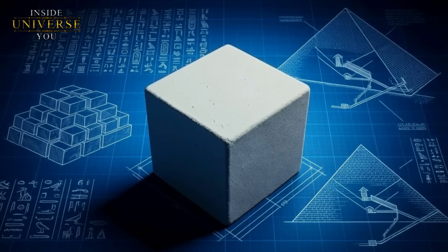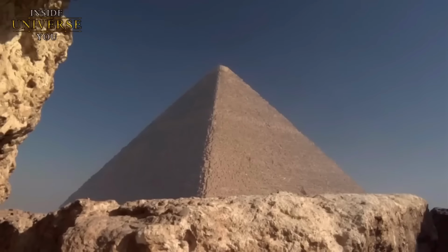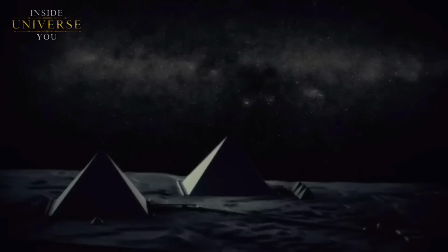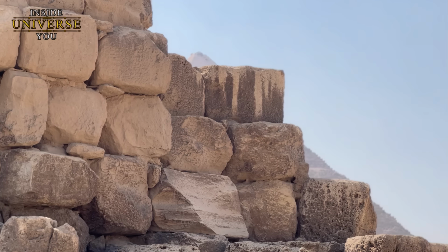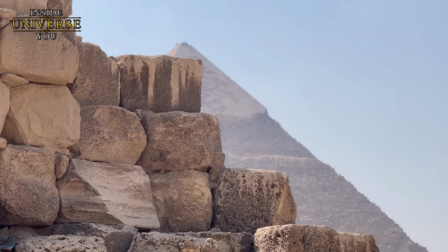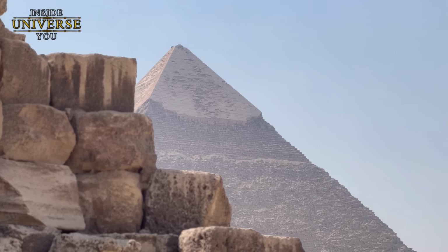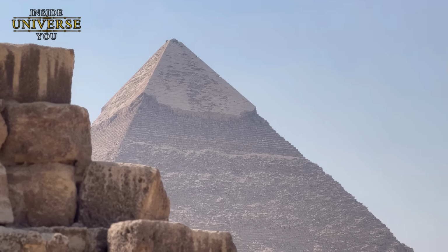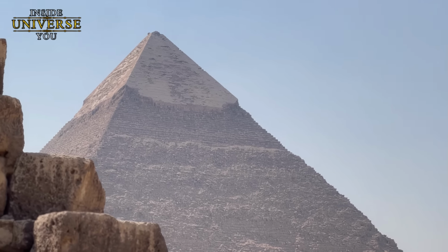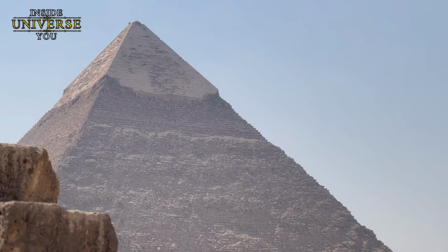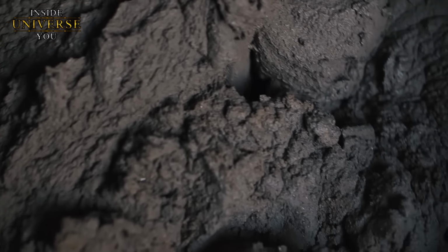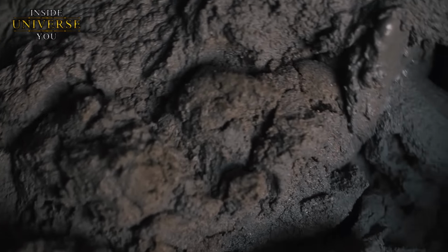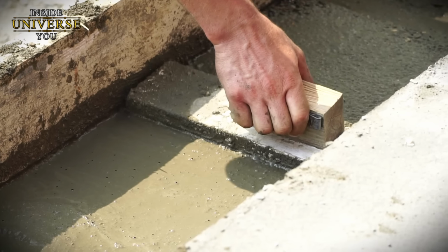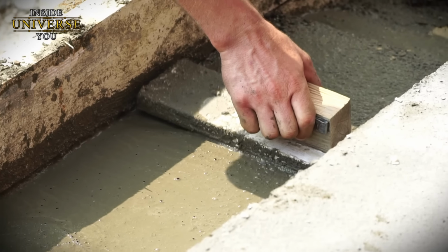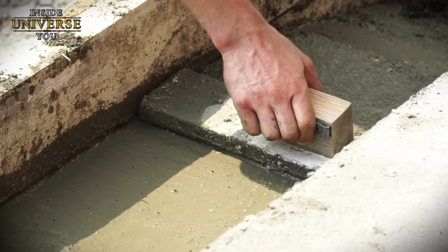Barsoum also discovered that the pyramid stones contain much more water than normal Egyptian limestone. Natural limestone from the Giza Plateau is dry. Man-made stone, however, traps water during mixing and hardening. Even more telling, minerals inside the pyramid blocks were found in a hydrated form, something that does not happen in natural limestone, but does happen when minerals form quickly from water.